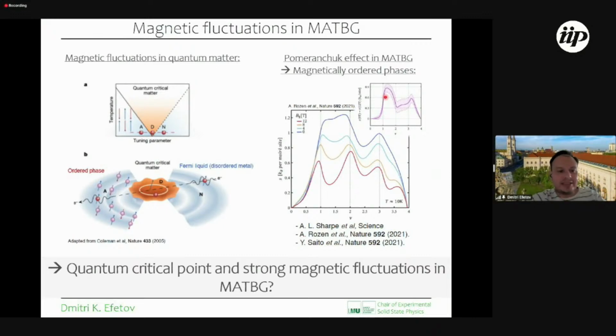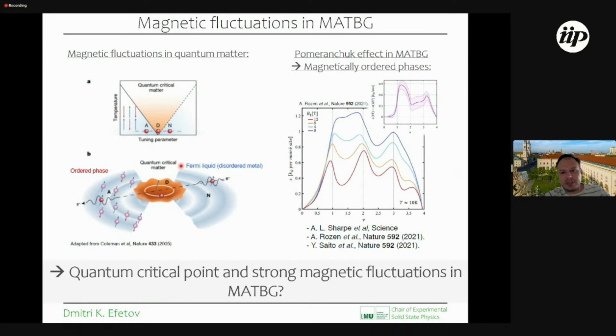Of course, in the past, many people have over the years studied strange metal phases. This is by no means a complete library of things, but there have been countless people working on this. But one popular assumption is that these strange metal phases appear close to magnetic phase transitions, where, for example, from a Fermi liquid to a magnetically ordered phase, and close to a quantum critical point, which is defining this phase transition, magnetic fluctuations can give rise to this extremely fast scattering mechanism.